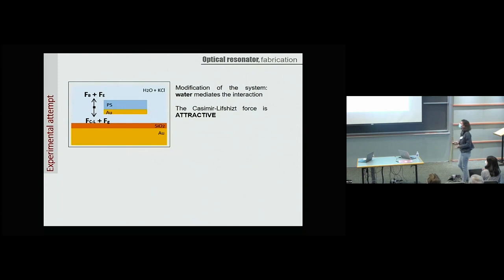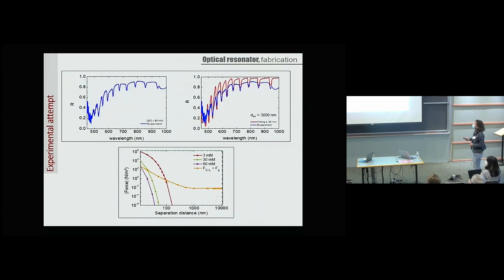We considered then water. So in this case now the force is going to be attractive, but we said, okay, let's try to observe macroscopically this quantum effect, although it is not repulsive. But anyways, we had a cavity, we had a fitting, we had a very large cavity. Well, you can see it already with the peaks, no? We checked also what we could expect from the electrostatic forces, and what we had to observe, which is this simple minimum here of one order of magnitude less than the observed cavity. Well, we were struggling with all these problems.